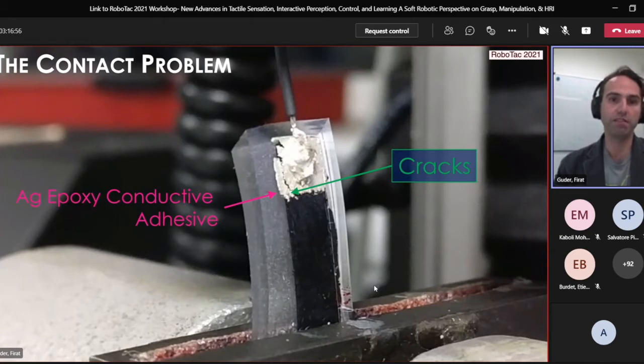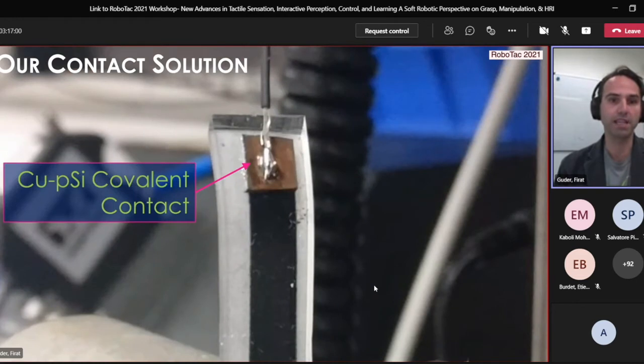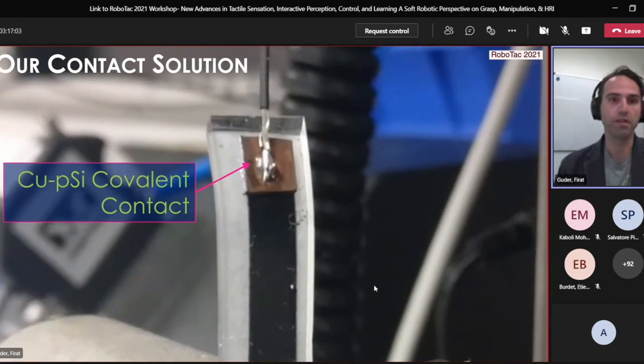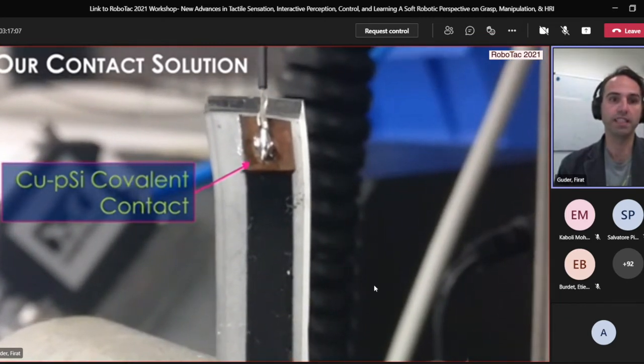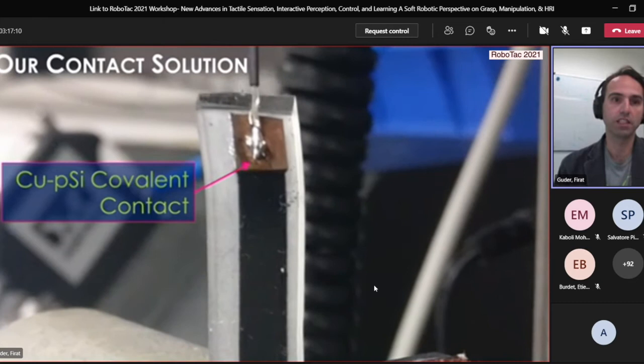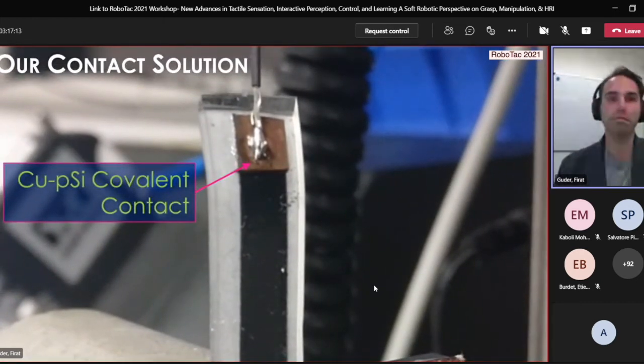So the solution that we have developed has completely eliminated this, and I will talk about it today. What it really is, is a material that consists of copper and porous silicon, which can be covalently attached to the silicone-based material. The way it works is that we decided to explore a method where we don't really change the chemistry. We're all using silicone-based chemistries to attach things together, and because they are very similar materials, they attach to each other covalently. Honestly, it's more or less the same material. They attach to each other covalently, and the bonding is very, very strong.